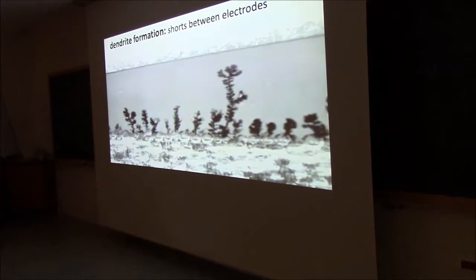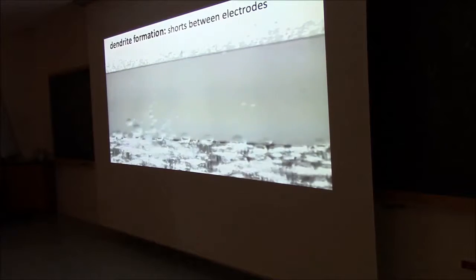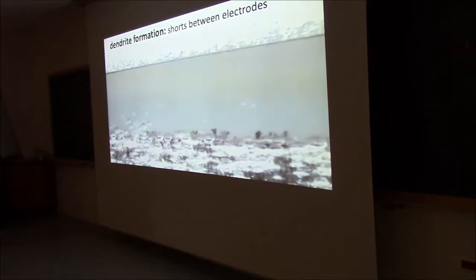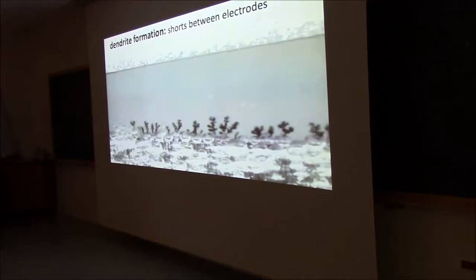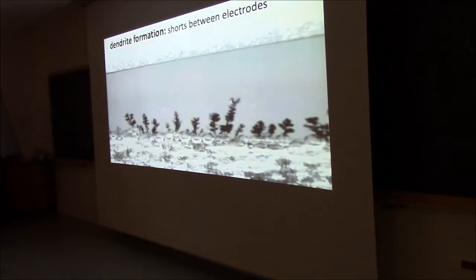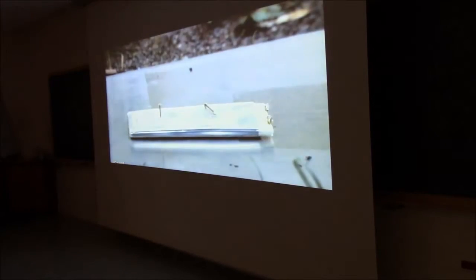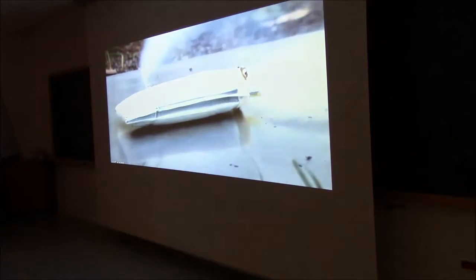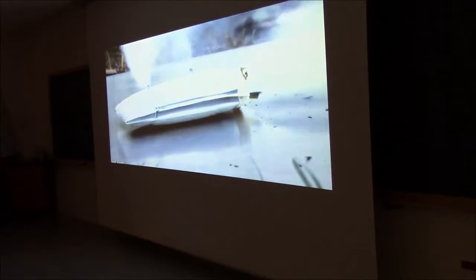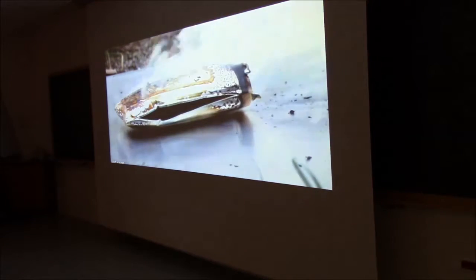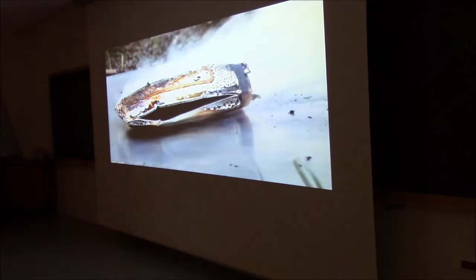But just to show you, the moment that something is shorted, you have this problem. So you can also find a lot of movies on YouTube where people on purpose short something. And how do you do that? You hit a nail through a battery. Then you have all the thermal runaway, gas happening, and at some point you have the fire, and this is what is happening in the end. So you can see that, of course, this short is extreme, but if you create a short and you have current running there, you have heat being created, thermal runaway. Now, this is why you have those problems with those batteries.